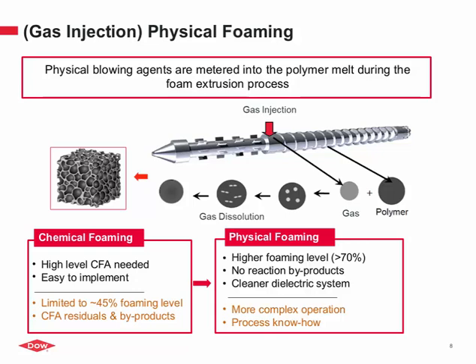Obviously, there is the chemical foaming approach where the compound is prepared with the chemical foaming agent. That's what CFA stands for. And it decomposes during the melt extrusion step. What happens is, relatively speaking, a high level of the foaming agent is needed. It's easy to implement because it's ready to go. There is no gas injection metering and so forth. However, it's limited to about 45% foaming level. And there is the other issue that this is essentially an impurity. What we are introducing itself is an impurity, and when it decomposes, it results in byproducts that are also electrical impurities. So the combination of all of this does affect the electrical properties of the insulation.